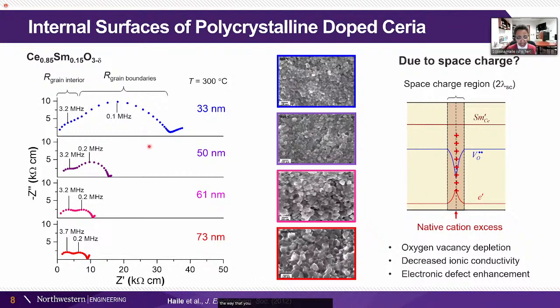So the way that you read these impedance spectra is basically the magnitude here along the real axis is equivalent to the DC resistance. And the larger the grain size, the smaller that resistance is, basically because we have fewer interfaces to traverse. And the explanation for this generally has been that there's a region at the interfaces that is inherently positively charged because it has a slight excess of cations. That positive charge induces a depletion of the positively charged vacancies, which are the charge carriers. And because you've depleted those carriers, that causes the conductivity to decrease.